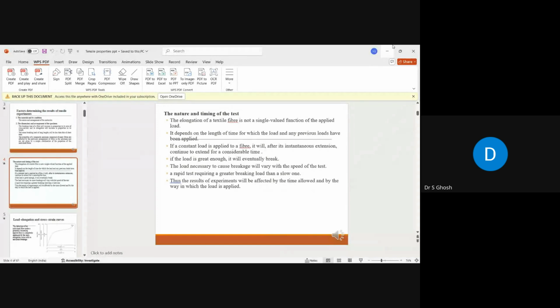So depending upon your requirement for your particular material, you have to select which test you want to carry out. It can be a tensile test, where you have to break the specimen within 20 plus minus 2 seconds, quasi-static loading. If you want creep behavior, then you apply a fixed load and see how the extension changes with time. If it is stress relaxation, then we apply an instantaneous extension and see how the stress decays with time. And if you want dynamic testing, then you apply a sinusoidal stress or strain on the system and study what kind of behavior results.